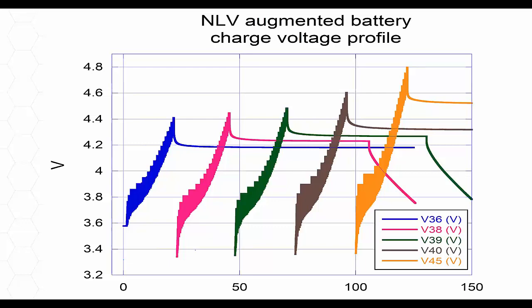We do this augmented battery testing. This is 36, 38, 39, 40, and 45 ampere hours. Okay, so the voltage, you can see that at the end of charge, the voltage here is about 4.8, which is higher than the 4.2 volt that is recommended by the cell manufacturer. But when we use NLV, we can go to higher voltages without destroying the battery.